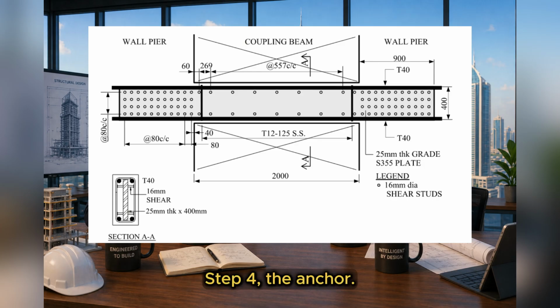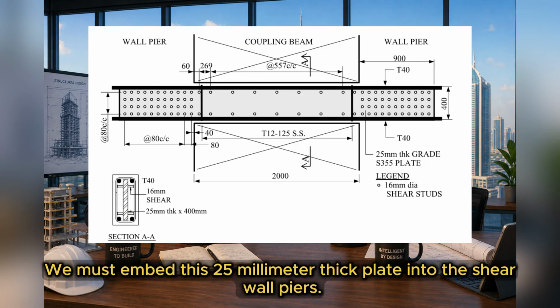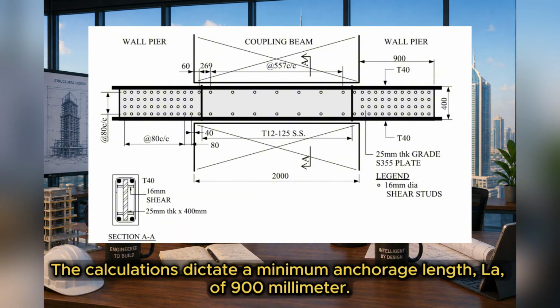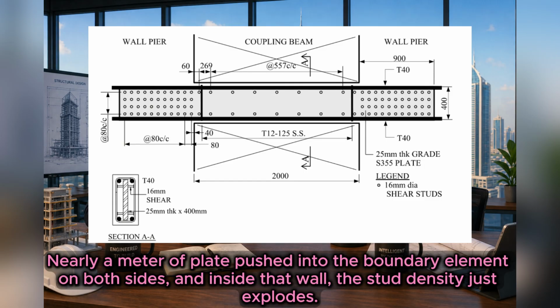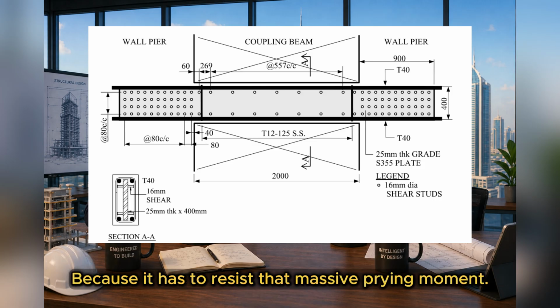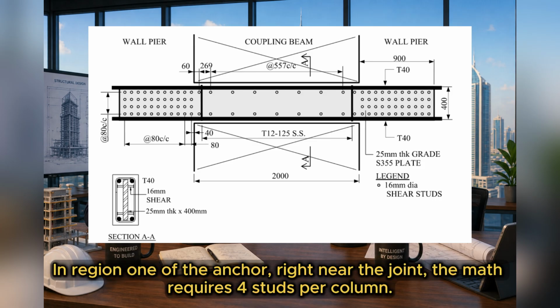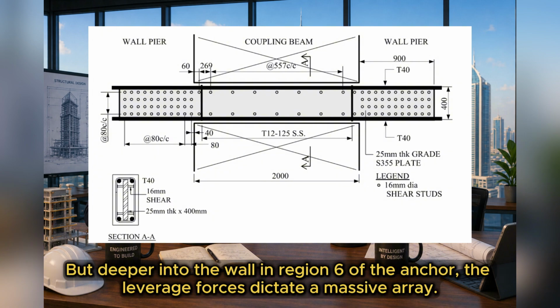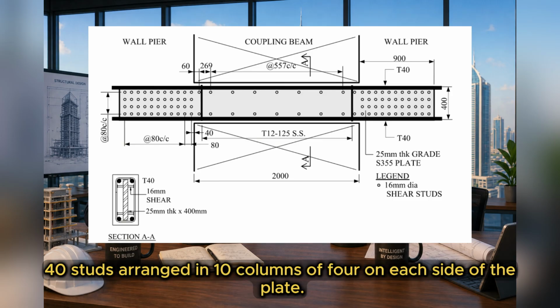Exactly. Step 4, the anchor. We must embed this 25 millimeter thick plate into the shear wall piers. The calculations dictate a minimum anchorage length, Lao, of 900 millimeters. Nearly a meter of plate pushed into the boundary element on both sides, and inside that wall, the stud density just explodes, because it has to resist that massive prying moment. In region 1 of the anchor, right near the joint, the math requires 4 studs per column. Okay. But deeper into the wall, in region 6 of the anchor, the leverage forces dictate a massive array. 40 studs arranged in 10 columns of 4 on each side of the plate.